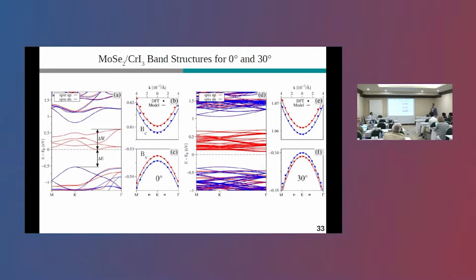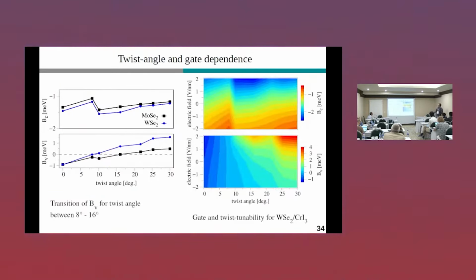So we can again reverse the proximity exchange splitting in the valence band by twisting, which is similar to what we have seen before. And again, we did the full twist angle and gate scan. So the conduction band splitting stays more or less the same upon twisting, but the valence band splitting can be very nicely tuned from negative to positive in this linear fashion by twisting from 0 to 30 degrees. And if you look into this electric field and twist angle dependence, you can find that the conduction band splitting can be tuned in the range of minus 2.5 to minus 0.5 millielectron volts, while the valence band splitting can be heavily tuned from about minus 1.5 to 4 millielectron volts upon twisting and gating.